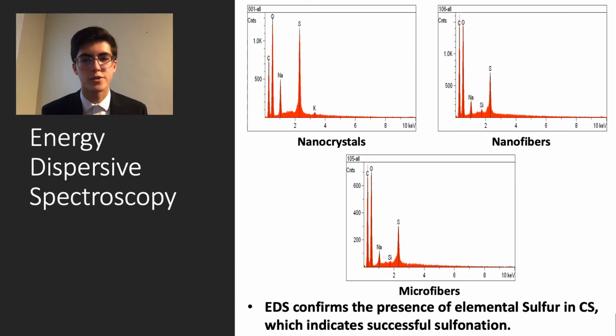Energy dispersive spectroscopy, or EDS, confirms the presence of elemental sulfur in each of the three materials, which combined with the FTIR data would seem to strongly indicate that sulfonation was successful for all three materials.